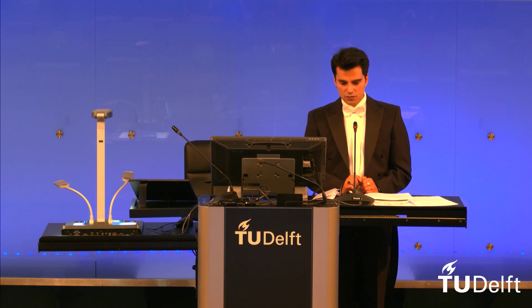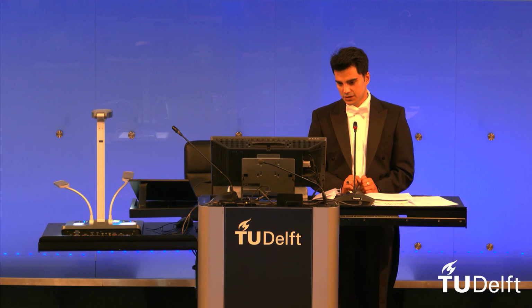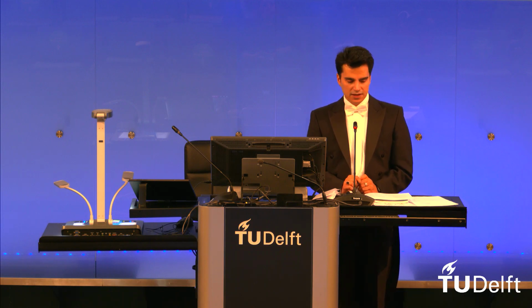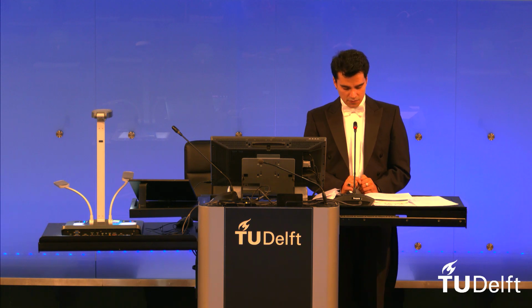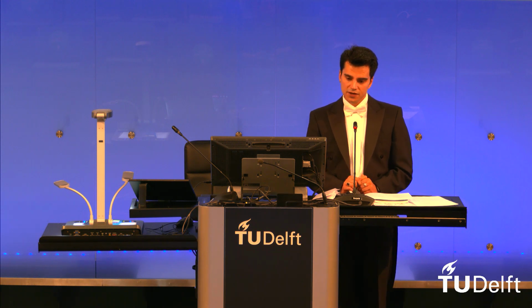In the settings, you might choose a higher power, the higher power of X-ray images, and also the higher resolution, by which you might get better resolutions of the images, which takes longer time. But in our cases, we have chosen the detectability of around 12 micrometer in each 2D image, by which it took us only a few hours, maximum half a day, in order to do for each sample.